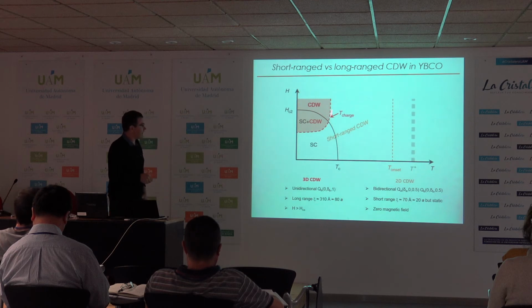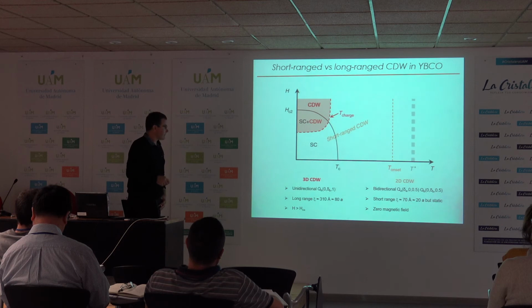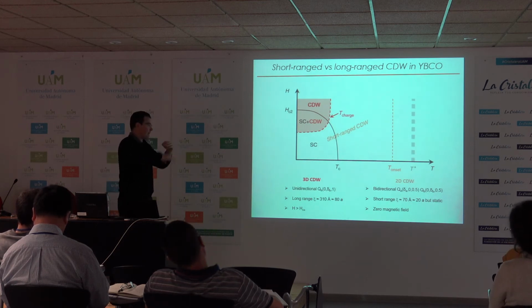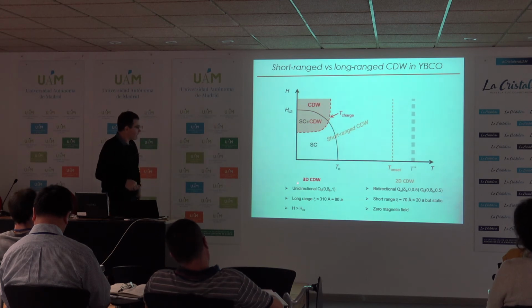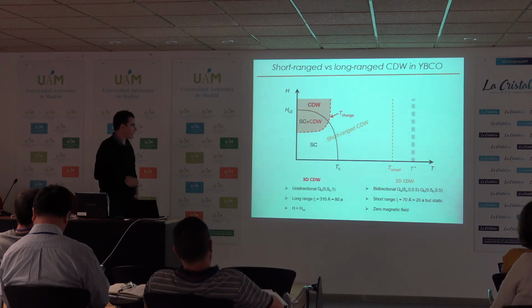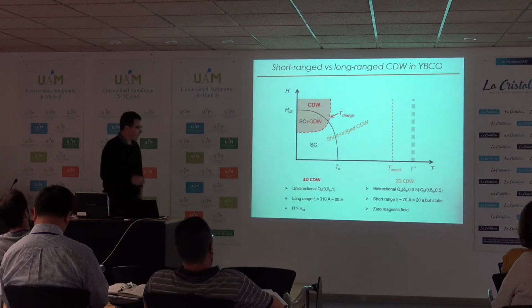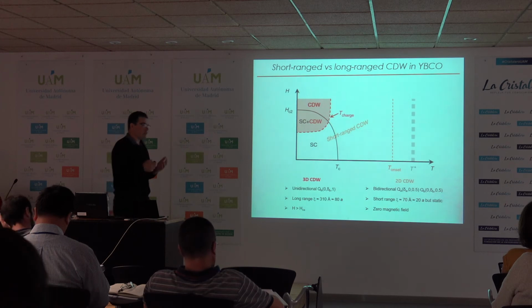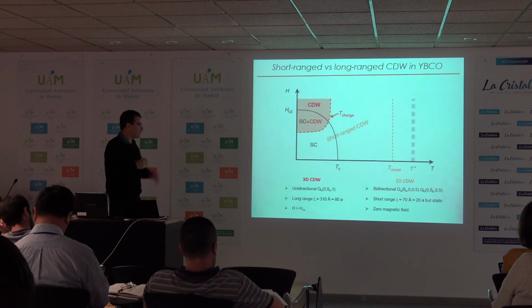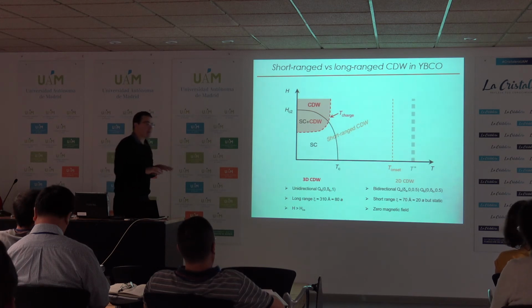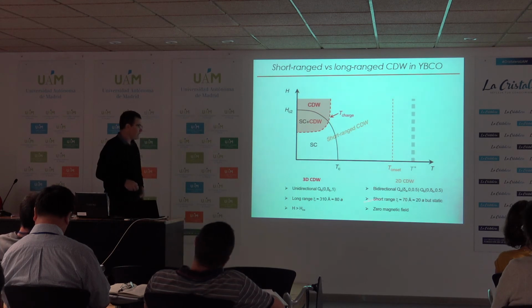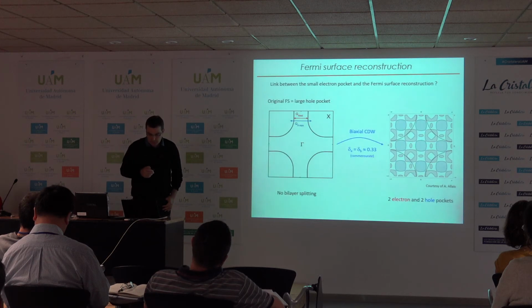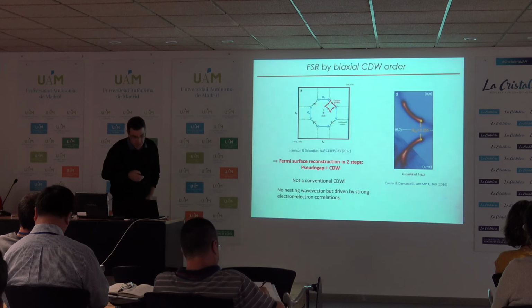The one discovered by NMR, where we see quantum oscillation, is a long range 3D charge density wave, meaning along the z-axis. This charge density wave has a modulation which is unidirectional. So this is long range, observed only above a certain field. And at a higher temperature, basically between TC and T star, X-ray measurement has shown the presence of what we call a 2D charge density wave, meaning that the correlation length along the z-axis is very small. This 2D charge density wave has bidirectional modulation and is observed at zero magnetic field. I'm not going to discuss that because my time is running out.